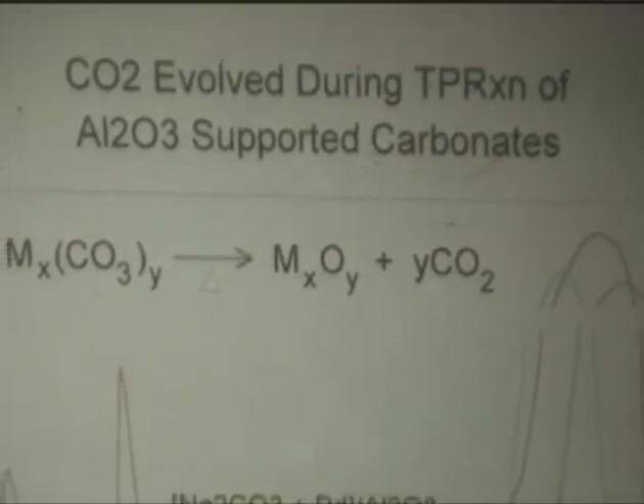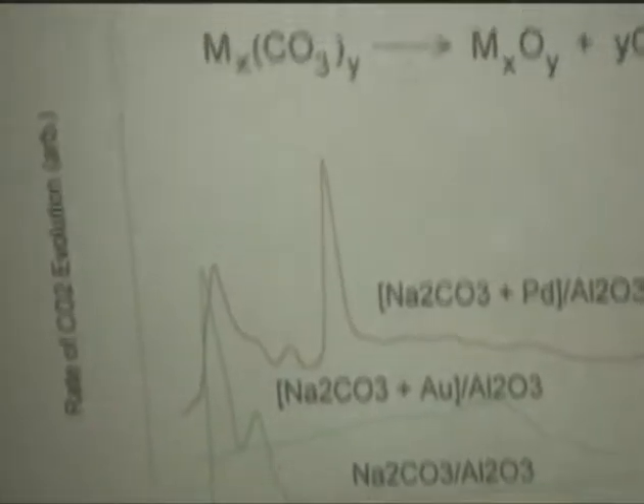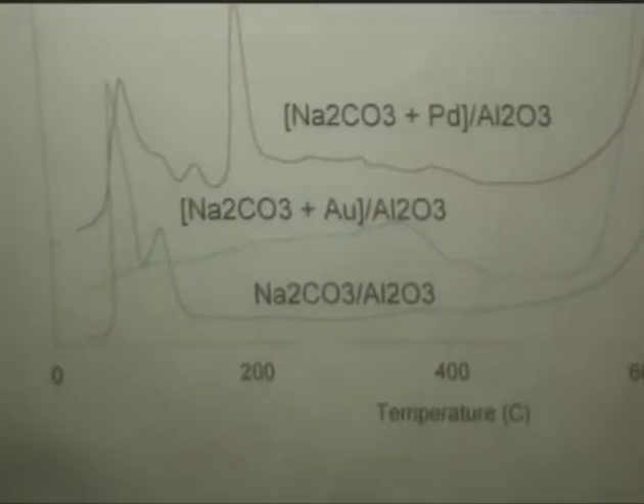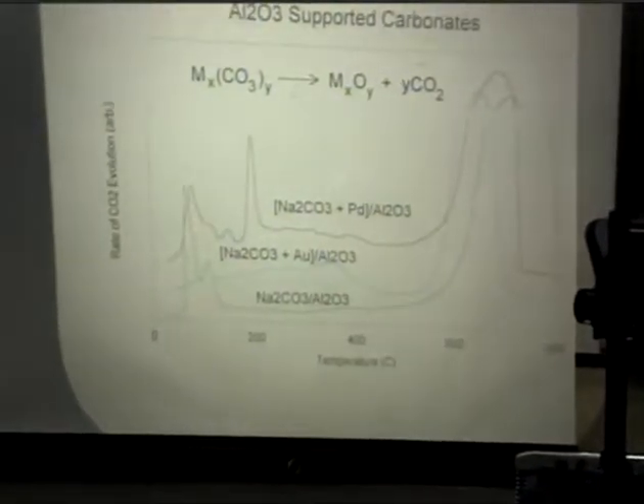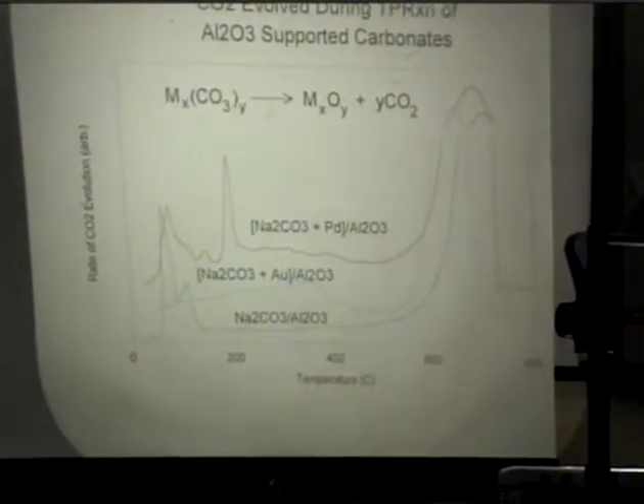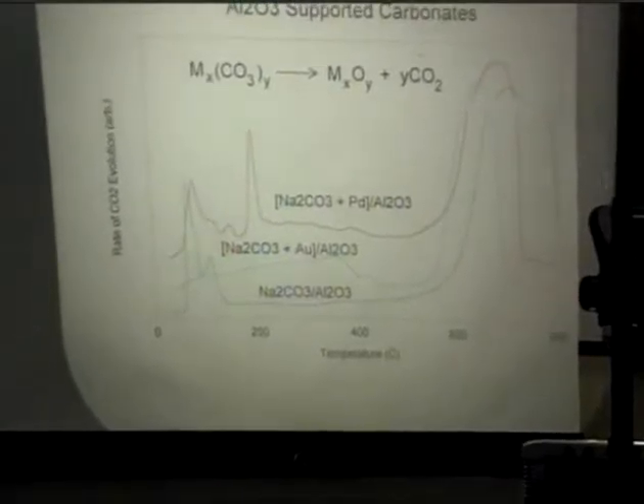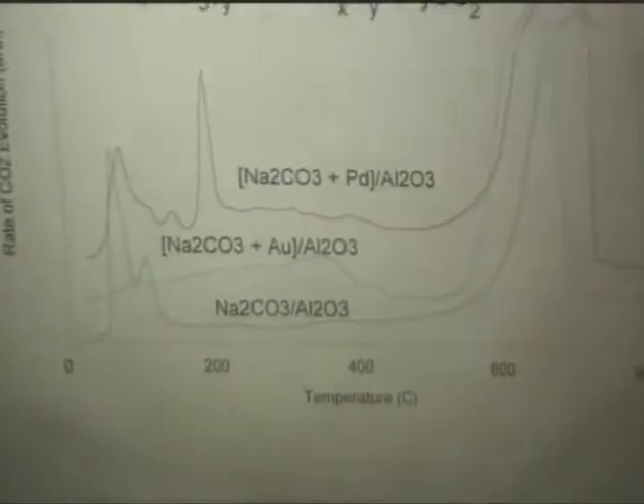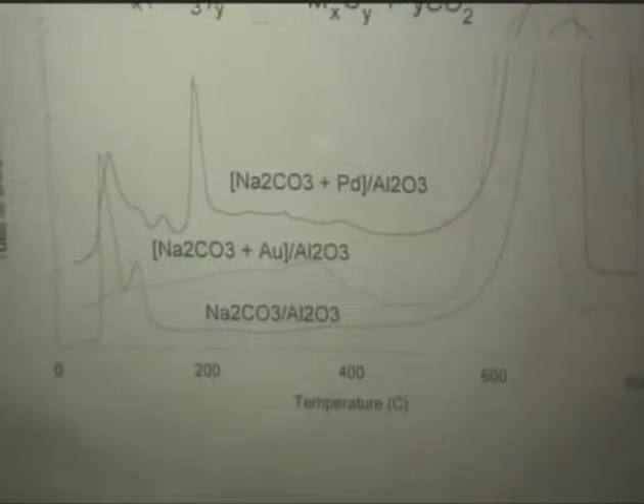Now, the classic test for carbonate is a thermal decomposition. Again, very simple. So this is a temperature program reaction in nitrogen, and we monitor it with a mass spectrometer, and we just look for CO2 coming off. Essentially what we see is that when sodium carbonate is alone, we see a desorption here, which is due to the desorption of water and CO2 that is present in the water, but that the sodium carbonate itself is very stable and does not decompose, at least on aluminum, until about 650, 700 degrees C.